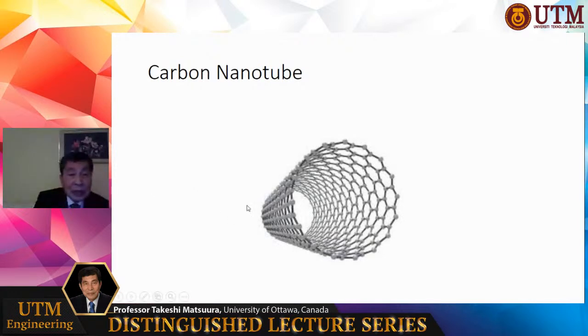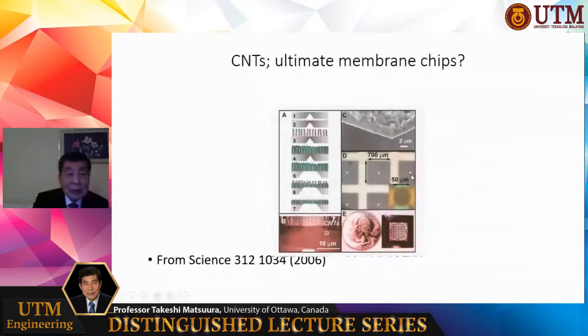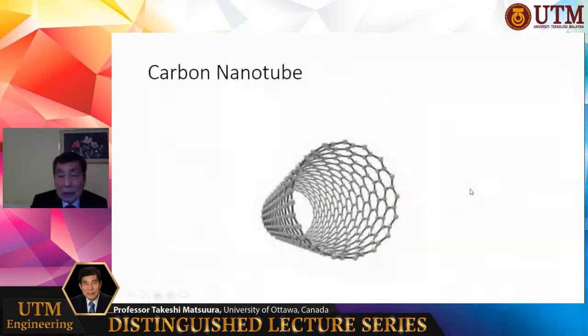A carbon nanotube has this structure. This is just one layer of carbon, and it has a cylindrical structure. There is a hole inside, and when water goes into this space, this surface is made of carbon material. Therefore, it is very slippery. Water slips on top of this surface. And so when water goes into this space, then water flows very fast because the surface is slippery. And you can increase the flux quite significantly when you use this carbon nanotubes.